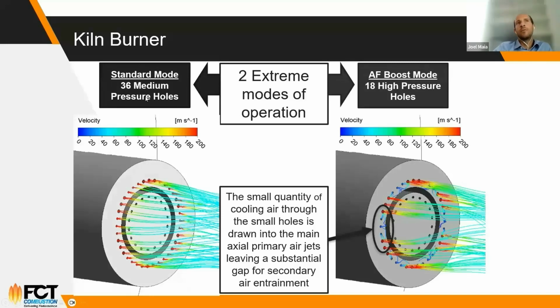When you have the standard mode, meaning all holes in operation, you would have a situation like this. And when you have the boost mode, only with the 18 holes, obviously there's a little bit of air coming out here just for cooling and avoid blockages. You would have a much higher performance of the burner. Not only in terms of velocities here, meaning higher momentum, but also you create space between these high velocity jets, and this space is perfect for sucking secondary air, which has the most oxygen in the kiln, into the flame.